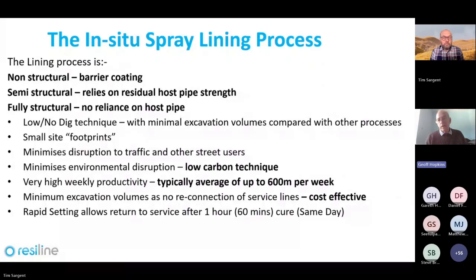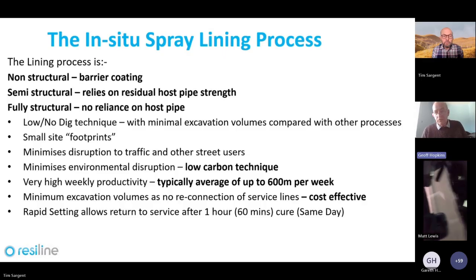Fairly typically we would expect a lining rig working around the UK to be able to line something like 600 meters a week. So a lining rig would do your 30 kilometers of network in a year, but that could go up or down. If you're out in the countryside, you could double it. If you're in central London or somewhere like that, you could probably halve it. But the reason it's minimum excavation is because there's no reconnection of service pipes required, so consequently it's very effective. A spray lining applied at 3 millimeters will block 6 millimeter holes. Since most service pipes are larger than 6 millimeters drilling, it doesn't actually block service pipes.